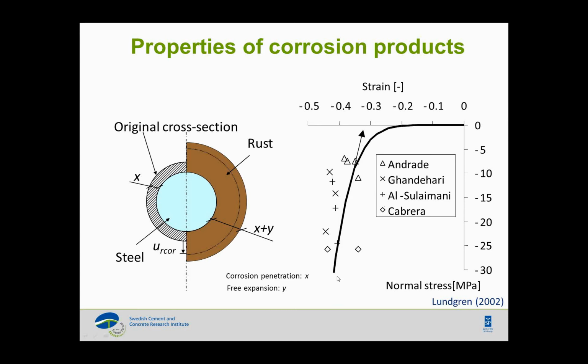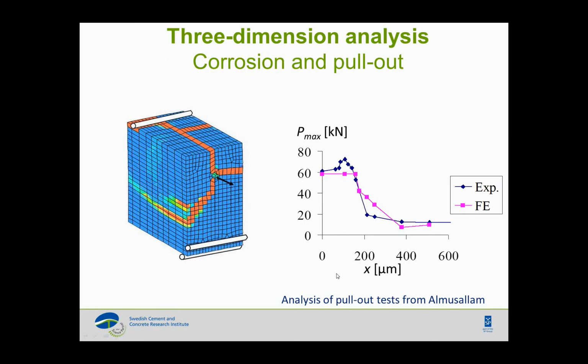The model works in a way that we have formulated this swelling effect in an interface element between the reinforcement and concrete in Diana. So what we have here is a concrete specimen with the reinforcement, and then this interface element in between the reinforcement and concrete, describing the bond and the corrosion in terms of swelling effects. The specimens are the ones that have been tested by Al-Musallam.